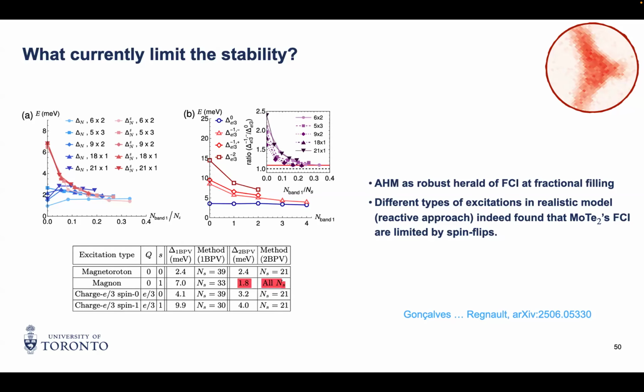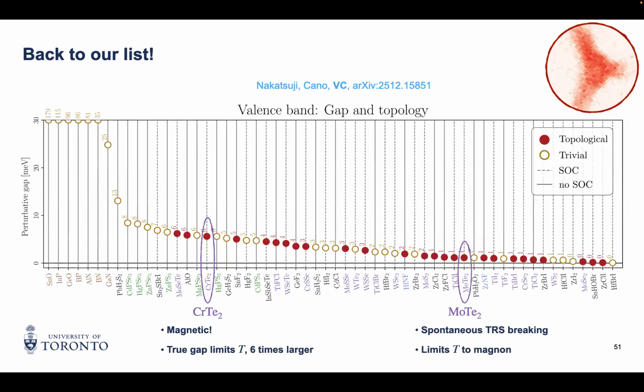So if you really want to push this topology to higher temperature, you also need to care about how is time reversal symmetry broken in my system. Is it spontaneous, as in this material, so driven by interaction? Or can I find another material where it's broken by a stronger effect? And again, you can go through the list and you find a close cousin to MoTe2, that's chromium ditelluride, and chromium has strong spins on the chromium, which can order very easily. So those ones, if you order them magnetically, they will break time reversal symmetry at much higher temperature, typically. I think in the few layer limit, 5 layer was shown to be ferromagnetic up to almost room temperature, so 250 Kelvin.